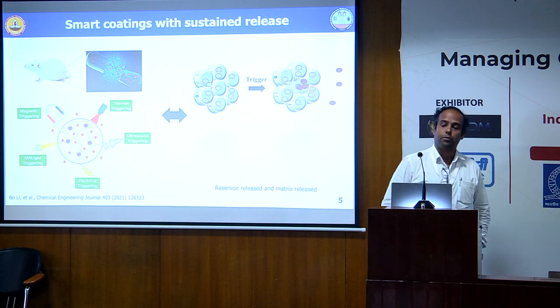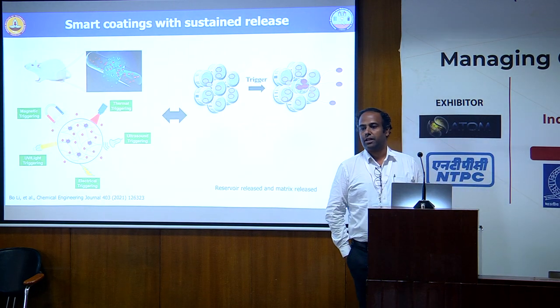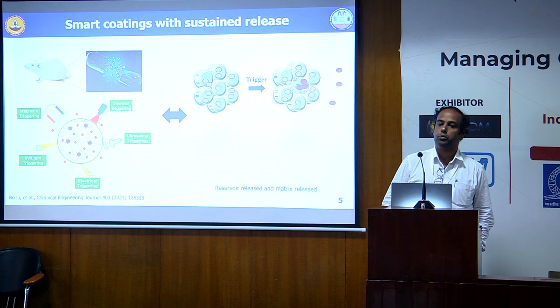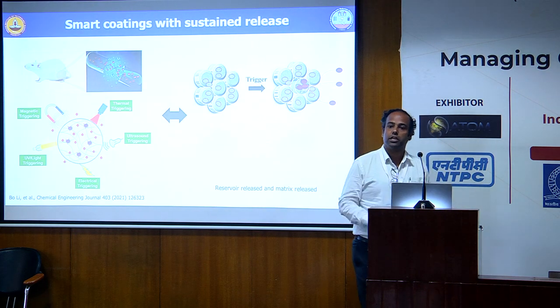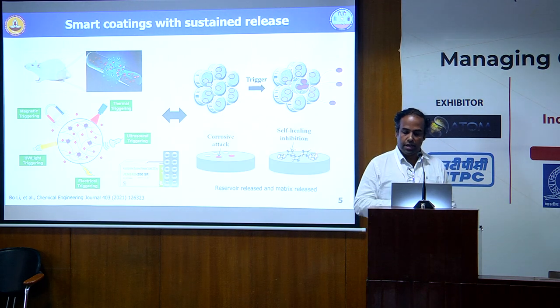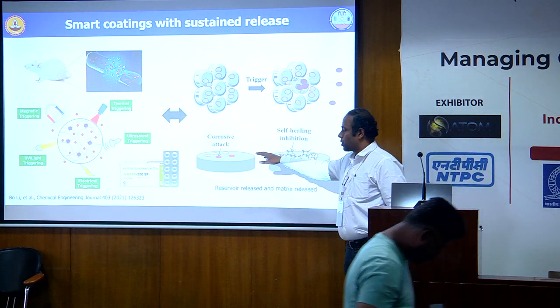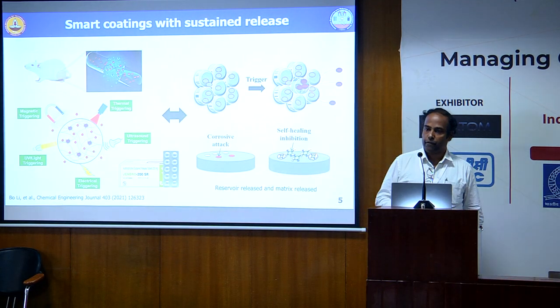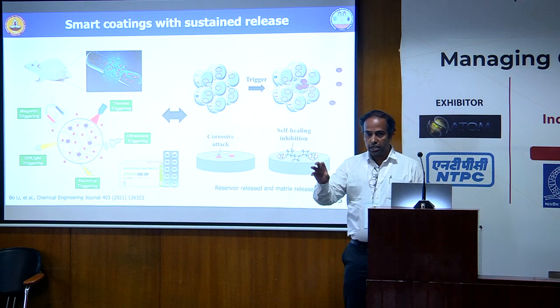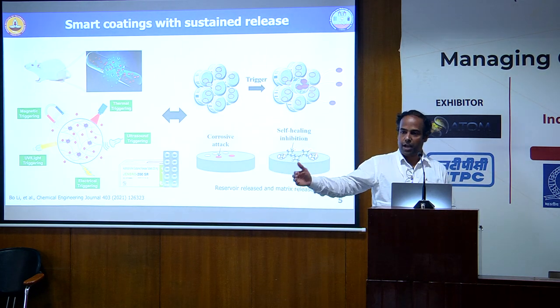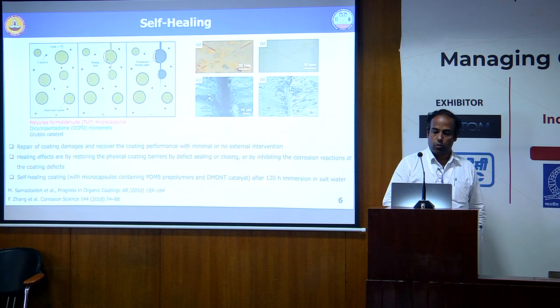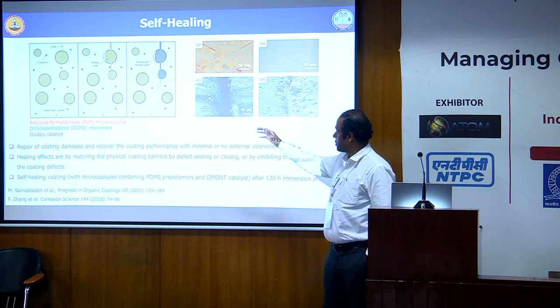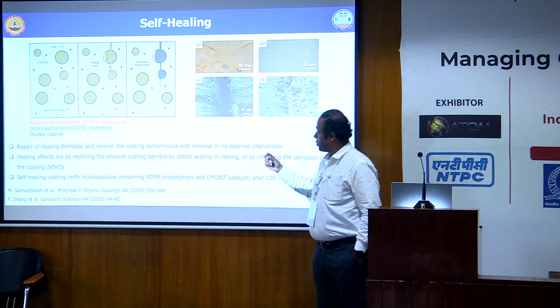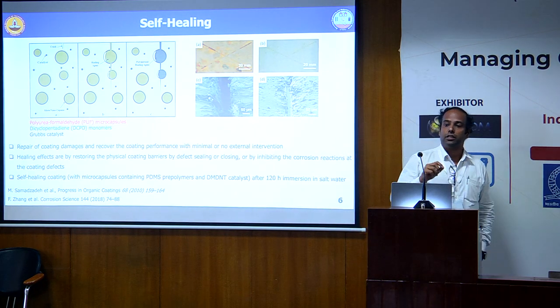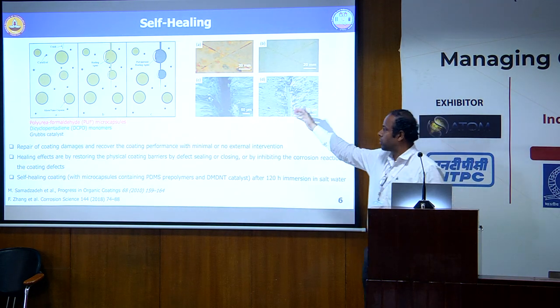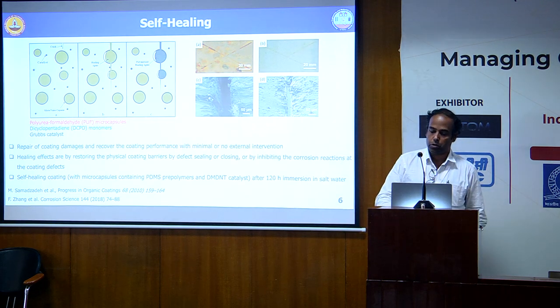In atmospheric corrosion, we always learn that when there is a reduction reaction at the site, the pH moves towards basicity. So pH can be one triggering point by which you can release these inhibitors. And finally, it can arrest the corrosive attack and self-heal the corrosion front. And this is not just releasing, it should be sustained over a period of time. Is it possible? That's what we wanted to try. This gives us a picture here. You see a scratch, and there should be particles or pigments which hold these inhibitors, and when there is a crack progression or a corrosion front, it should release and inhibit the corrosion front.